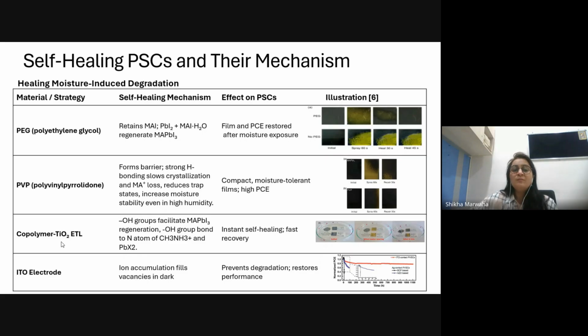Similarly, if I say copolymer TiO2 ETL, so instead of using a normal titanium oxide electron transport layer, if we make use of a copolymer titanium oxide layer, then the hydroxyl groups of water, because we are exposing it to water, facilitate MAPbI3 regeneration. With the use of this particular copolymer, the hydroxyl group bonds to the N atom of NH3+ and lead iodide, or PbX2, whatever material we have here. It forms a bond with this, and with time, the water evaporates. So it is basically self-healing, with instant and fast recovery.